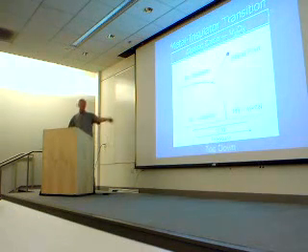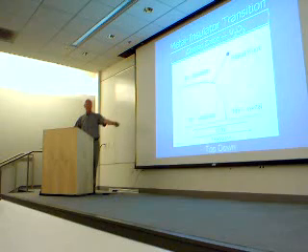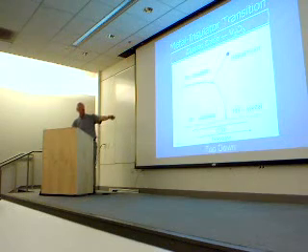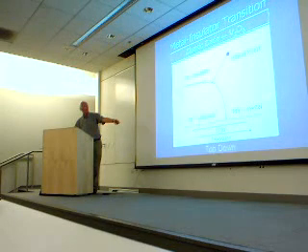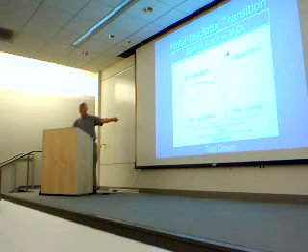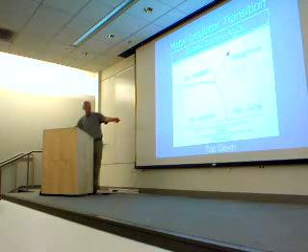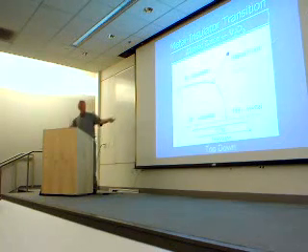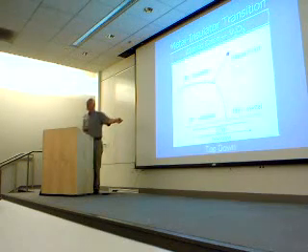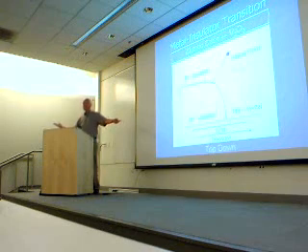Let's go top down. We start up here as a metal, where you don't quite know whether it's going to turn into an insulator. But at small enough U, it'll just be a nice metal. Up at high temperatures, it's going to become an insulator somewhere as U gets larger and larger. And this is exactly what Mott talked about. He proposed that if you pull the atoms apart, going to low pressure, at some point it'll always become an insulator, independent of whether it's ordered or not.